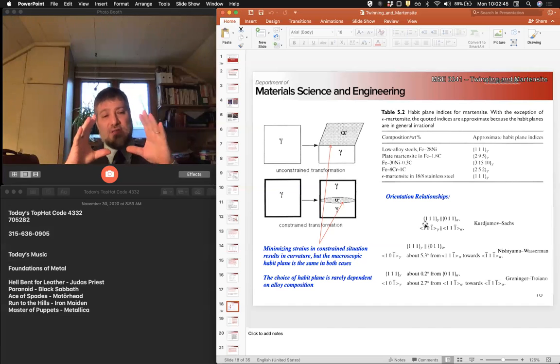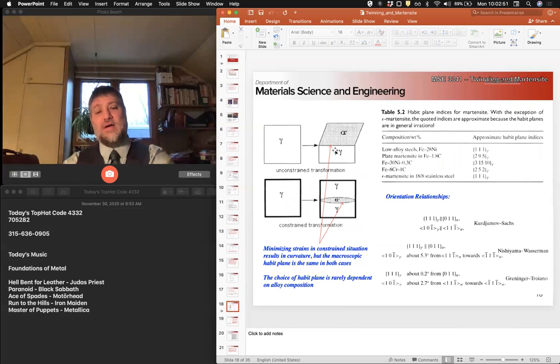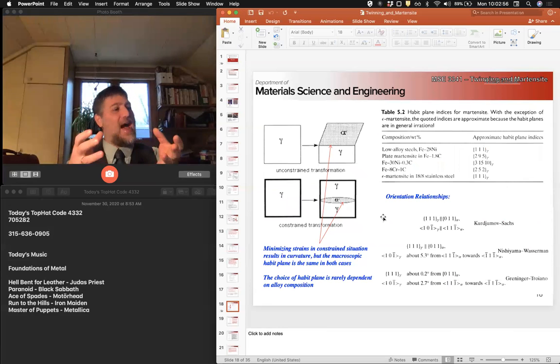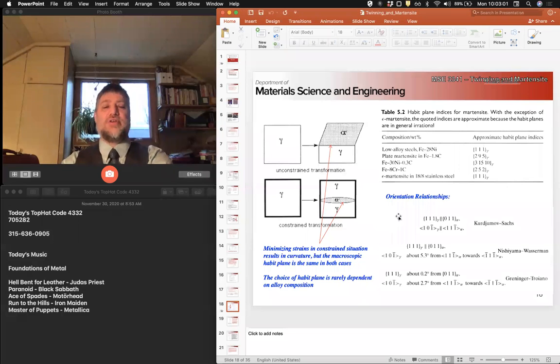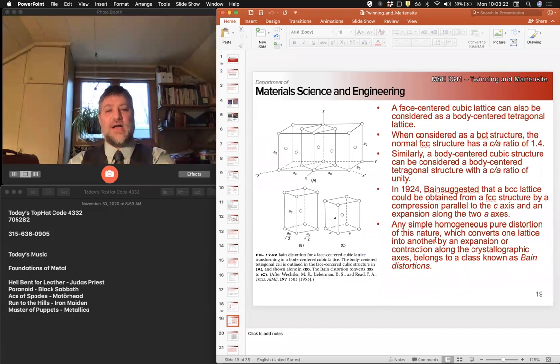Now, the thing about Martensite is in steels, the transformation pathway is dependent on the amount of carbon that you have. And the volumetric strain that you have is dependent on your carbon concentration. So we never actually observe any of these ideal orientation relationships. It's always somewhere in between because the carbon content is not always spot on for these to occur. And we'll talk about that on Wednesday.